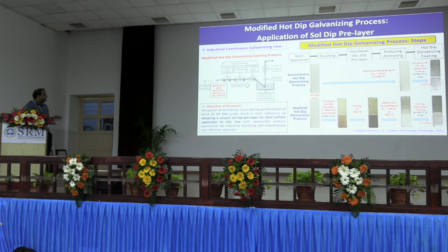So the idea is, can we develop a single process which will not require any change in the process parameters in a continuous galvanizing line, and we will get good galvanizability. In this modified hot dip galvanizing process, the problem can be mitigated with the application of an iron based sol dip pre-layer just before annealing treatment on the steel sheets, so that this iron based pre-layer will be cured and reduced during the conventional annealing atmosphere of nitrogen and hydrogen used in the continuous galvanizing line, that is the reduction atmosphere, and so we will get a thin metallic layer just before dipping into the molten metal bath.